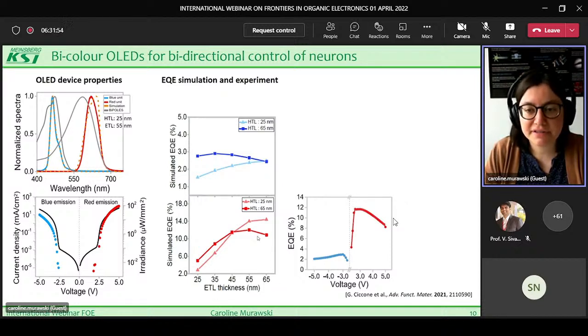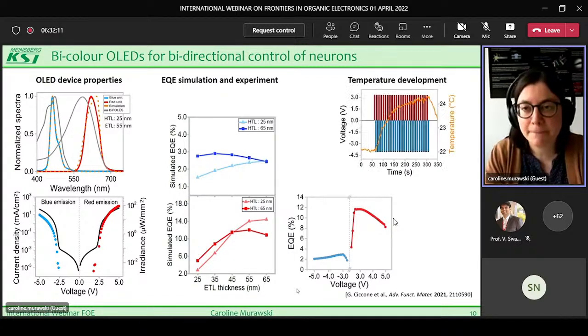So in the devices that we fabricated with these thicknesses, we achieved around 12% EQE in the red, and the blue is up to around 3% EQE. Remember that this is a fluorescent emitter, therefore you can't expect too much from this.